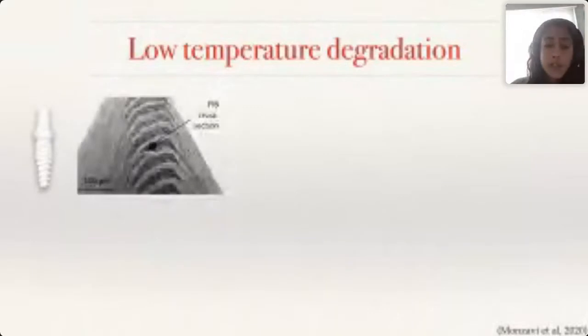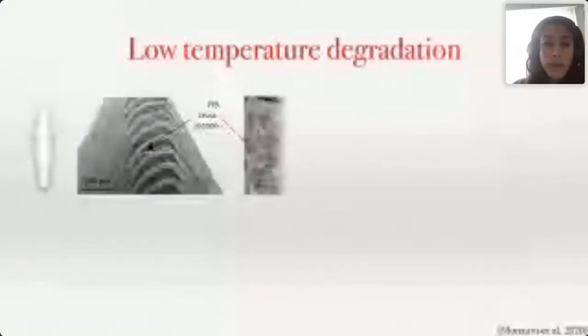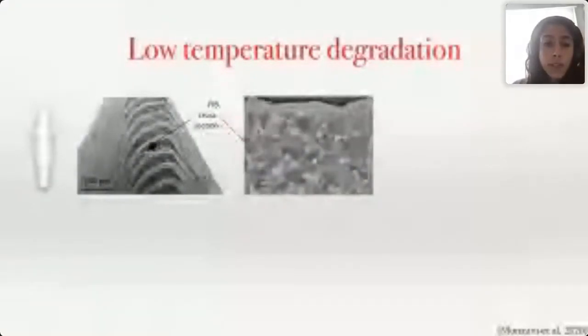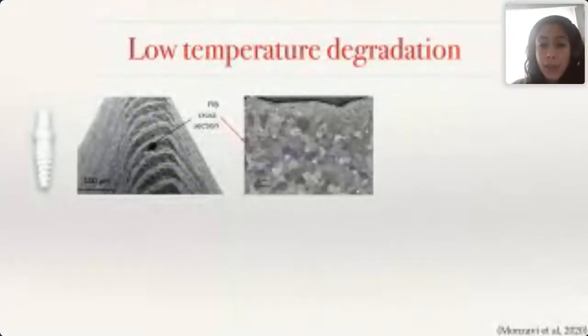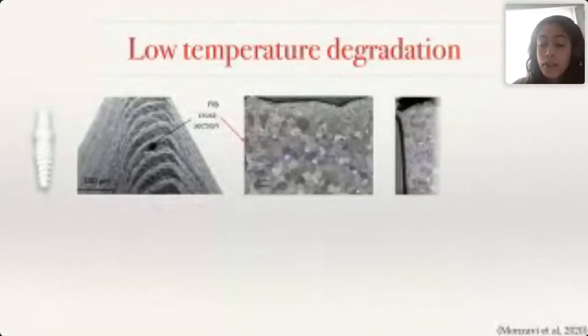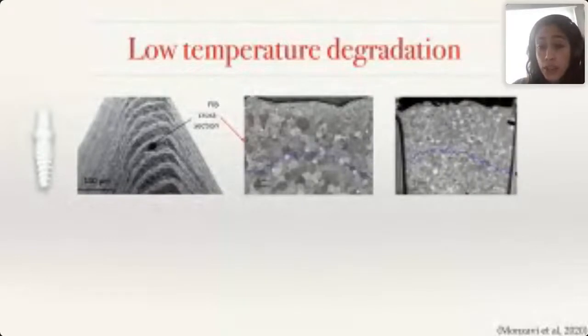So what we did in this study was we first took an image of the thread of the implant. We used the gallium ion cut, made a small cut, and then microscopically evaluated that cut to see what has happened to the grains following aging.